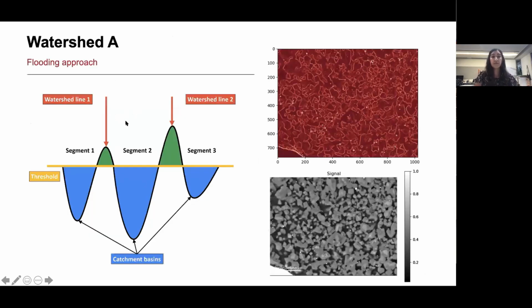The first watershed approach is called a flooding approach. For those of you that aren't familiar with watershed image segmentation, essentially, by using the boundaries of these grains, we can fill them with water, just like you would in a topographic image. And then we can threshold along that point. So all of these basins would be the area of our grains.